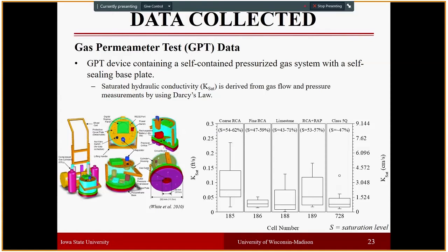And we have the gas permeameter test data, which gives us an idea about the permeability of the base layers of each test section. So coarse RCA, as expected, had higher permeability. On the other hand, fine RCA and the class 5Q conventional aggregates placed on the large stone subbase test sections have the lowest permeability, which is again expected. Permeability is directly correlated to the grain size distribution, and these results depend on the saturation level of the test sections, therefore moisture content has a great impact on the data that we collected here.